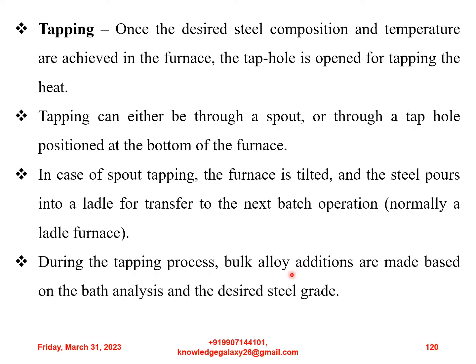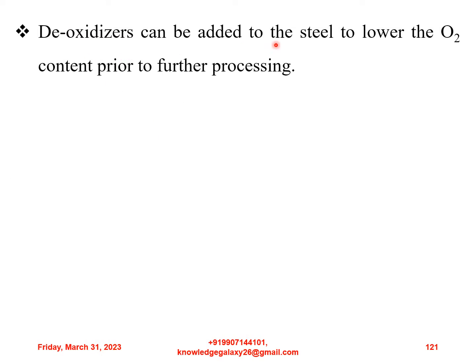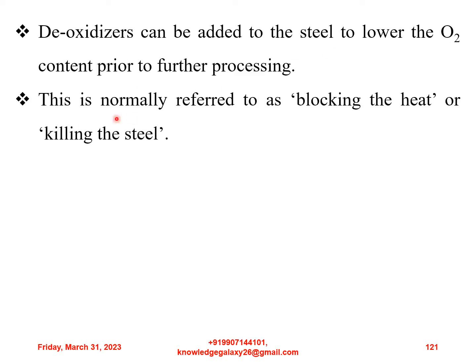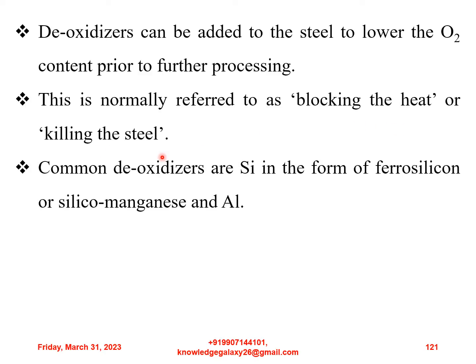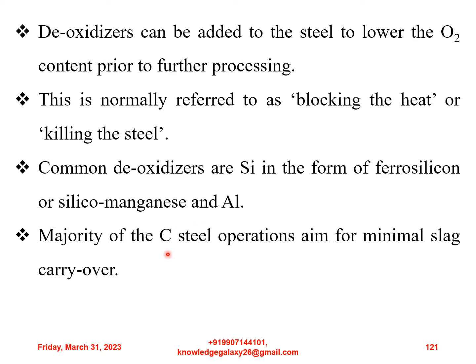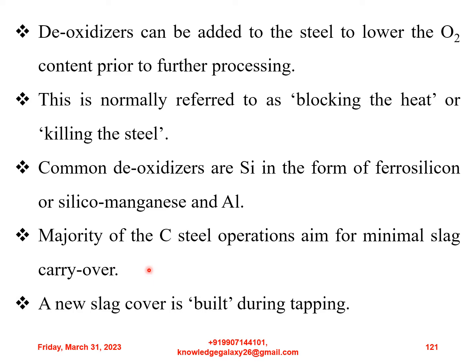During the tapping process, bulk alloy additions are made based on the bath analysis and the desired steel grade. Deoxidizers can be added to the steel to lower the oxygen content prior to further processing. This is normally referred to as blocking the heat or killing the steel. Common deoxidizers are silicon in the form of ferrosilicon or silicomanganese, and aluminium. Majority of the carbon steel operations aim for minimal slag carryover. A new slag cover is built during tapping.